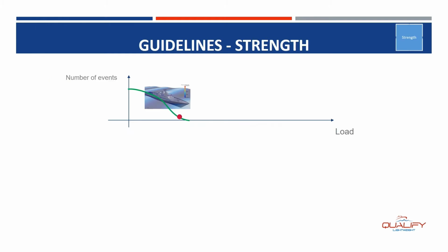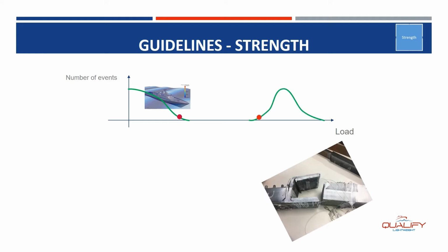If we want to discuss the first box, the strengths, basically the strength is the fact to define the loadings on the joint, their numbers, their amplitude, so as to map the design load, the maximum load that may appear to a joint. This will be compared to the strength of the joint with the average scattering and the characteristic load, which is close to the minimum failure load. This is fairly easy through a project like Qualify by testing. It defines the margin between the load and the strength, which is indeed the safety factor.